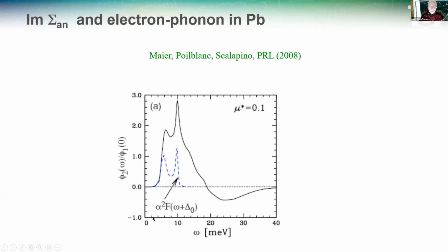Now, if you take the phonon density of states and you shift it by the gap, you see that again you have two peaks. And if you look closely, you can see harmonics of the peaks here, which correspond to the fact that the BCS equation is nonlinear. So this was sort of the smoking gun experiment for phonon-mediated superconductivity in electron-phonon systems.